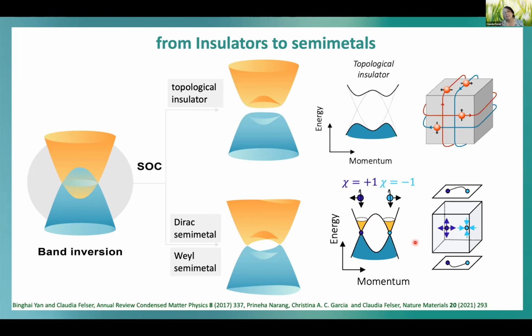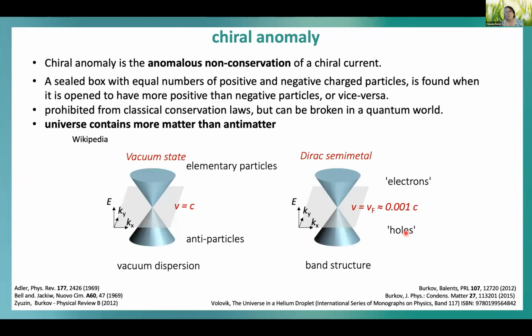Magnetic monopole - and so this leads to very special surface states which connect these two points in the bulk, and this is the so-called Fermi arc. So why are we super excited about this? Because I think the Weyl equation is a very special equation. It allows for a chiral anomaly, which is also a hot topic in high energy physics, because it might be an explanation for the origin of the universe and the asymmetry between particle and antiparticles, because this is an anomalous non-conservation of a chiral current under certain circumstances.